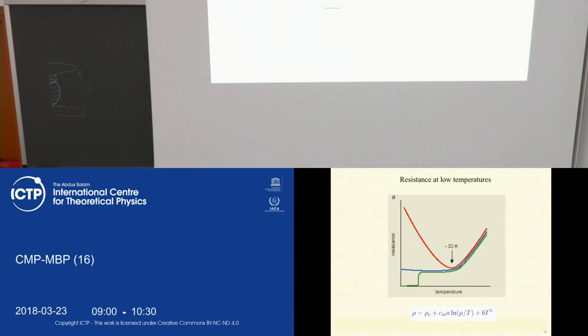The blue curve is copper, where resistivity saturates, but what is seen in these alloys is an increase of resistivity at lower temperature. So what Kondo did, he constructed a very simple perturbative theory coming from high temperatures, and first of all he discovered that the theory is renormalizable, and the interaction of local moments with conduction electrons produces logarithms. So the resistivity indeed grows logarithmically when the temperature is lowered. This effect is of paramount importance for nanostructures. Would I have time, I will talk about it. Would I not have time, we will find some other way to speak about it.